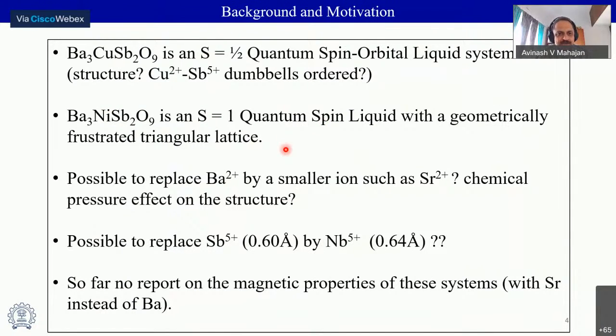So at that point, we were wondering whether we introduce chemical pressure by replacing the barium ion by the much smaller strontium ion, and whether this replacement would give rise to perhaps a change, or whether the crystal structure remains the same. How does that impact the magnetic properties and so forth? It turns out it was also possible to replace the Sb, which is non-magnetic 5+, by Nb, niobium 5+, because of the very similar ionic radii. And it turned out that there was no report on the magnetic properties of the strontium analog. It's still a copper spin half system.